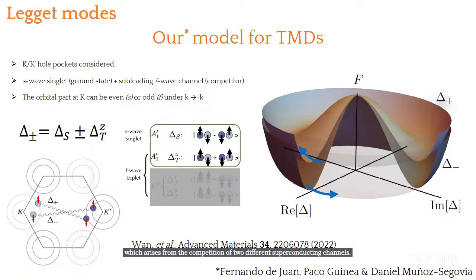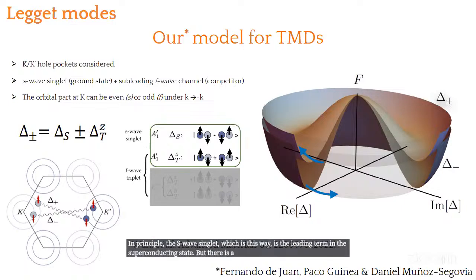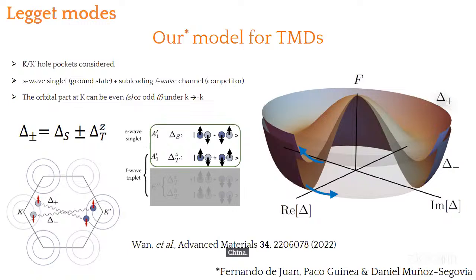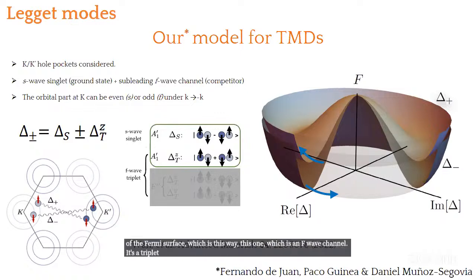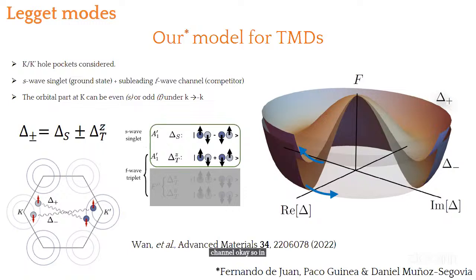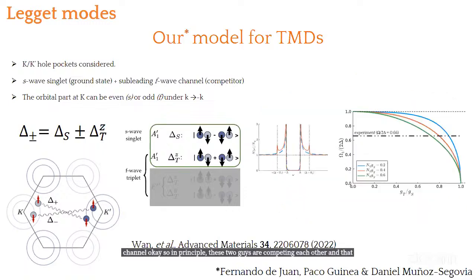Okay, so Fernando, Paco, and Daniel have modeled this particular system, where you can see that only the K pockets are considered. In principle, the S-wave singlet, which is this wave, is the leading term in the superconducting state. But there is a subleading channel, which is enabled by the structure of the Fermi surface, which is this one, which is an F-wave channel. It's a triplet channel, okay? So in principle, these two are competing with each other, and that renormalizes the density of states outside of the gap.